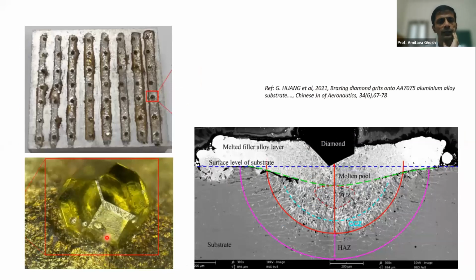So they saw that yes, the brazing could be done successfully. And if you see the diamond here, the diamond is nicely brazed with the filler. There is good wetting. And ultimately the alloy is also fused with the aluminium nicely. So it is a hybrid joining, you can say. The brazing is taking place between the diamond and the filler alloy, and between the filler alloy and the aluminium it is almost like welding, because the melting point of the filler is above the melting point of the substrate.